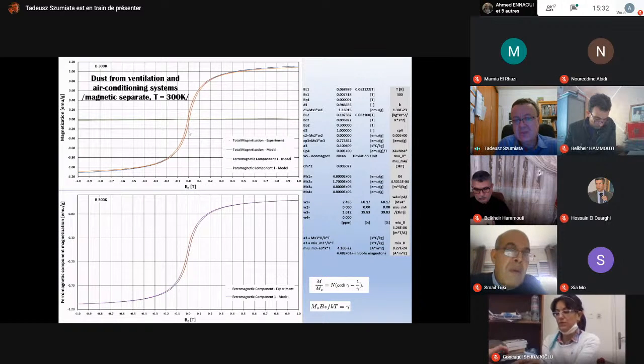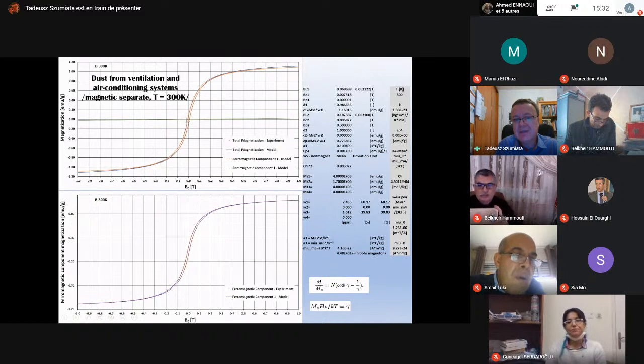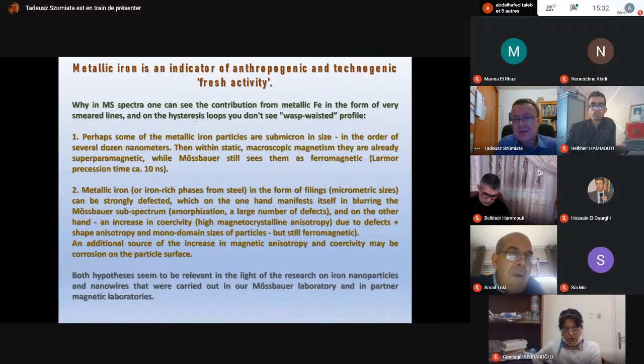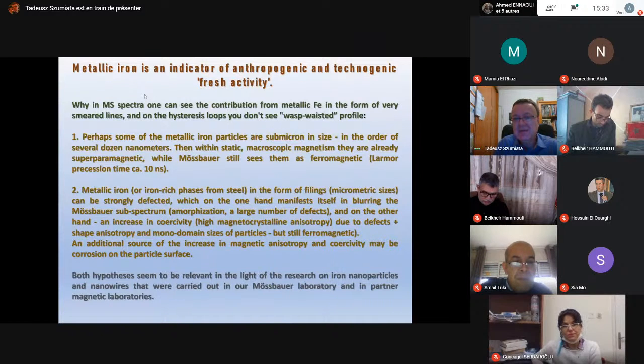One hysteresis loop is enough, and the value of the coercivity is very typical for just magnetite at room temperature. So still we have an inconclusive method, or we cannot understand something, and we must think for a moment why we can't see the traces of metallic iron looking at room temperature hysteresis loops.